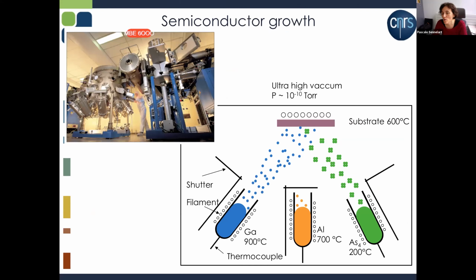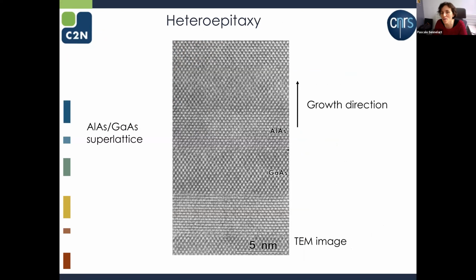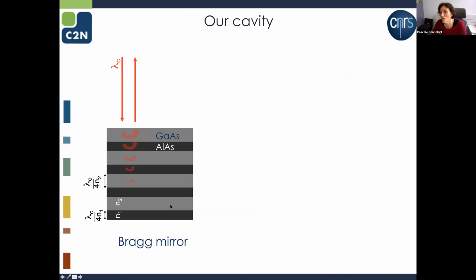So let's start with the Semiconductor Quantum Dot. So we start with the growth. Basically, you have this growth chamber where you have an ultra-high vacuum, and you can evaporate different key elements, gallium, aluminum, arsenic, and you send that on the substrate, and you can open and close these shutters here. So if I open one of these two, I can grow gallium arsenide, but then I can close this one and open this one, and I can grow aluminum arsenide. By doing that, I will have the first ingredient of my source, which is a superlattice. I can have alternating layers of aluminum arsenide, gallium arsenide, like this. Here you see individual atoms in this image. This is a TEM image. And this is a basic ingredient to fabricate an interferential mirror, a Bragg mirror.